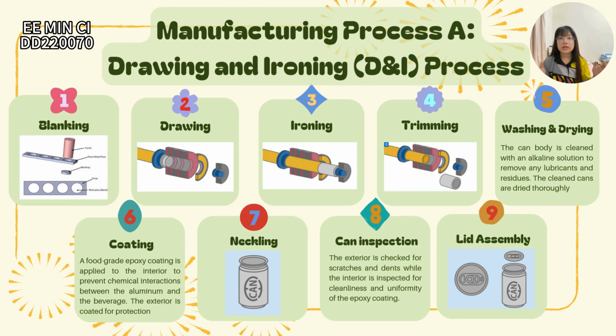A large sheet of aluminum alloy is fed into a blanking press, and a circular blank is punched out with minimal material waste. The second step is drawing, in which the blank is deep drawn into a shallow cup shape using a drawing die. The third step is ironing, in which the shallow cup is forced through a series of ironing rings under high pressure. The fourth step is trimming, in which the excess material at the open end of the can is trimmed to achieve a uniform height. The fifth step is washing and drying.